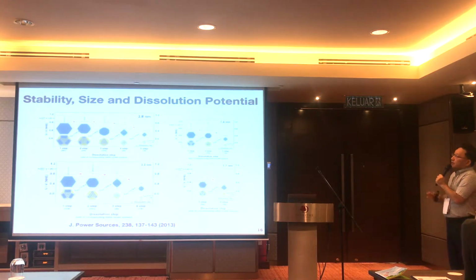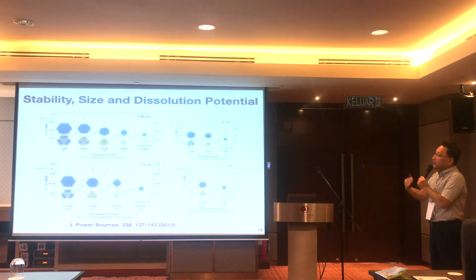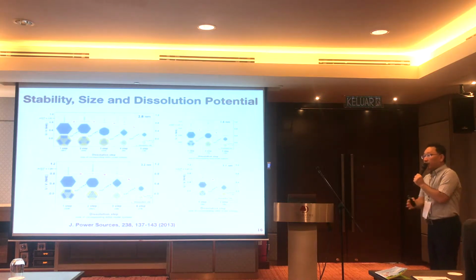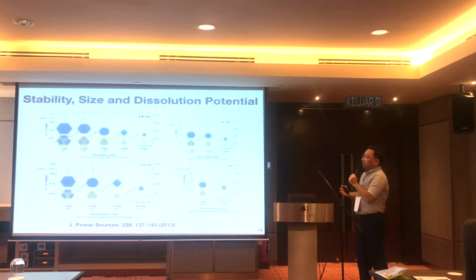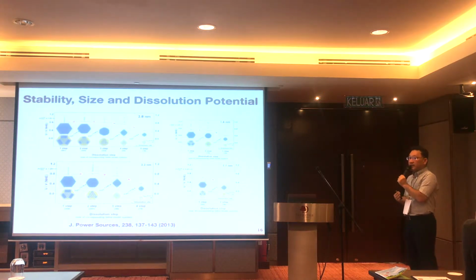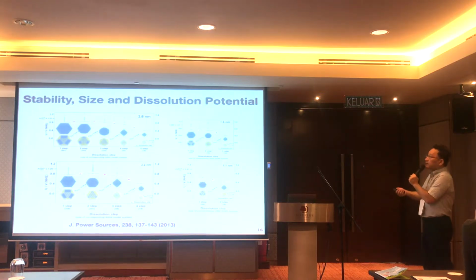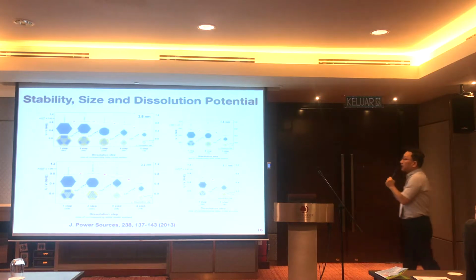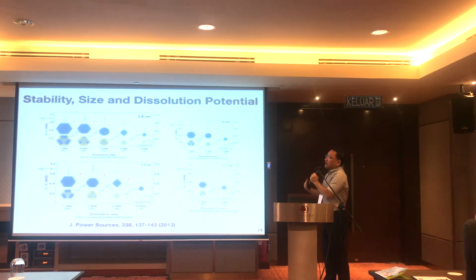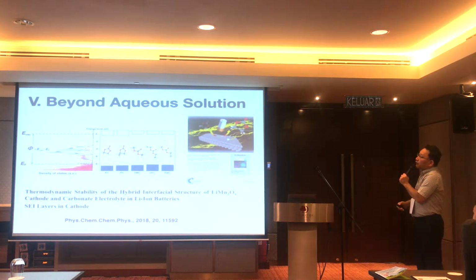So one or 2 nanometer platinum particles dissolve below 1 volt. How big should the particle be to stay above 1 volt of dissolution potential? Because people want to know. Companies like Ford, Hyundai, Honda, Toyota want to know how big a platinum particle they have to use to keep the dissolution potential above 1 volt. Our computations show that even 3 nanometers is not enough to keep 1 volt of electrochemical stability. We need much bigger than 3 nanometers, which means you are losing the benefit of platinum nanoparticles, right? The only benefit of nanoparticles is that you have a much wider surface area compared to bulk. So if you're using very huge nanoparticles, you're losing the benefit of platinum nanoparticles. But anyway, this is unfortunate, but single pure platinum nanoparticles are not a good catalyst material for hydrogen-driven electric vehicles.